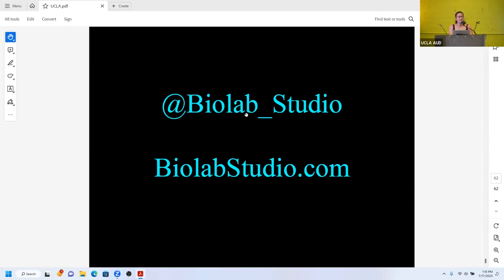Yeah. So basically how mycelium works is it really activates its structural properties once it's dead. In the case of the tower, they grew the mycelium bricks offsite and then brought them in already dried, and then they assembled it like that. So once it's dried, it doesn't require any growth conditions such as humidity, because it's already an inert material. Mycelium structures like that last around 20 years before they begin to biodegrade, which in my opinion is enough for an architectural structure. I think our products and buildings should biodegrade back to the earth and not outlive us all.